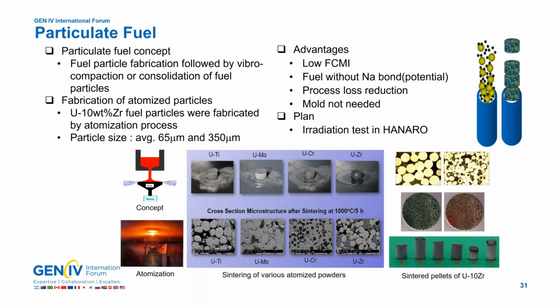This technique is used to fabricate research reactor fuels for our HANARO reactor. So by using this equipment, we fabricated particulate fuels of uranium-10 zirconium. We can make different sizes by changing the rotating conditions. And we fabricate particles and consolidate them by a sintering process to this size. Then this fuel can be inserted in the claddings. So the advantage of this particulate fuel is that the particles can directly contact the cladding from the start.